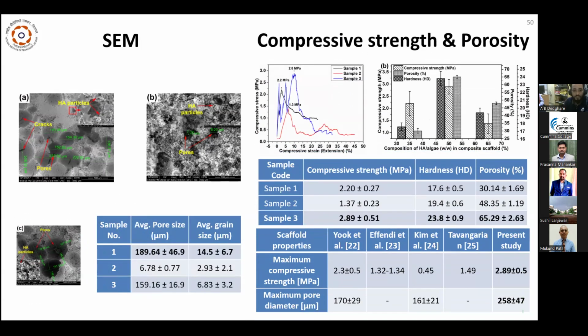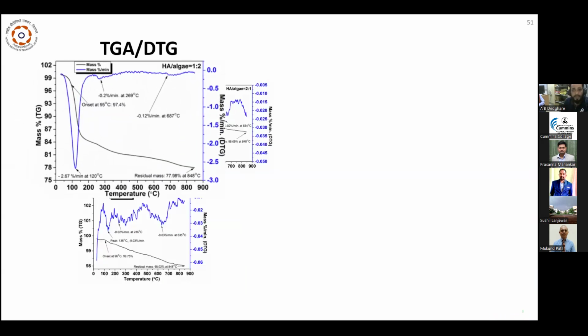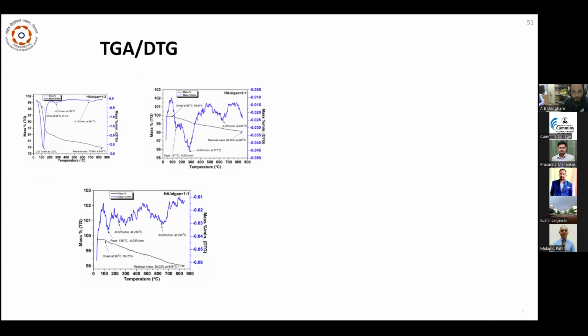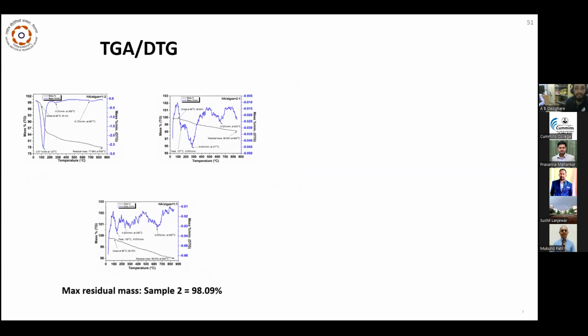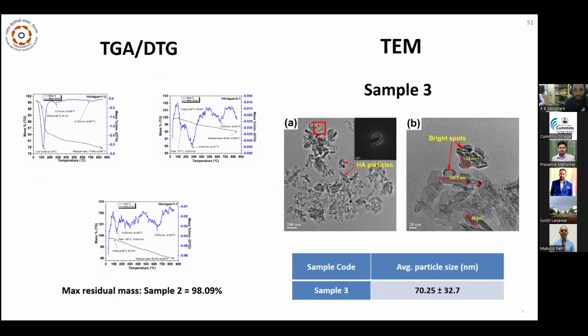Then the SEM analysis is also performed to show the morphology. Then the mechanical properties, which are compressive strength and porosity, which are important. For sample 3, compressive strength, hardness, and porosity are observed to be higher. Then TGA analysis is performed, which is basically to observe the thermal stability, where the residual mass is higher for sample 2.